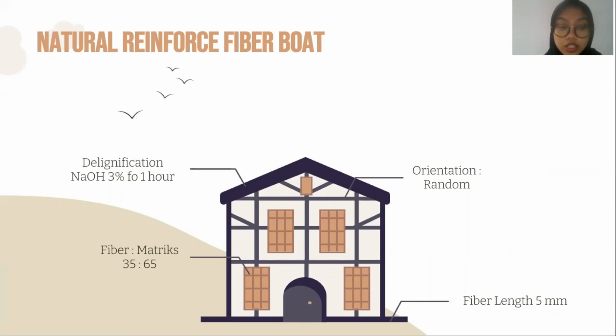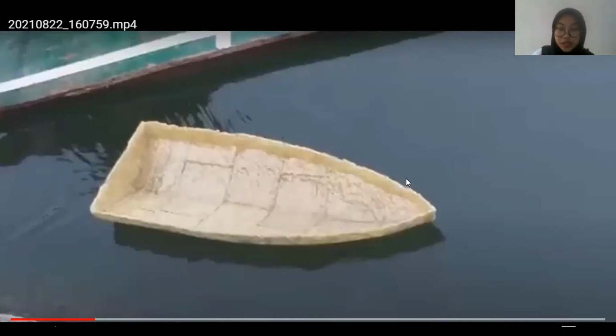Constraints occurred during the fabrication process, namely when applying resin to the top of the holes in the mold. This happens because the dimension of the layer used is too small, so there are some parts of the top of the holes left blank in the mold, and for its application a layer that covers it is used. Then, when applying resin to the top of the holes, the mold will be tilted first, so that the small pieces of layer do not fall off, and so that the layer can stick perfectly according to the shape of the mold. The following is the NRFB when tested in water.